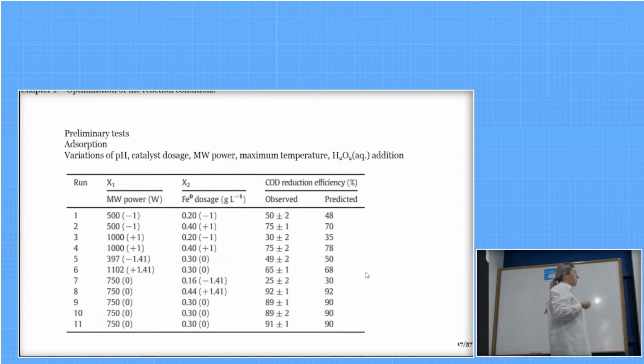Then we started to optimize the process by using preliminary tests, and we investigated adsorption, which was not expected, but we tested anyway to verify the zero-valent iron conditions. And we studied the variations of pH, catalyst dosage, microwave power, the maximum temperature, because we were working with microwaves, and the addition of hydrogen peroxide. The variables that significantly impacted the process were only microwave power and zero-valent iron dosage. And we tested these experiments by observing the reduction in chemical oxygen demand.